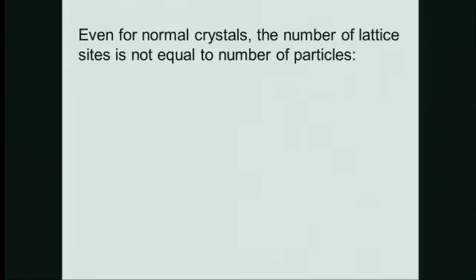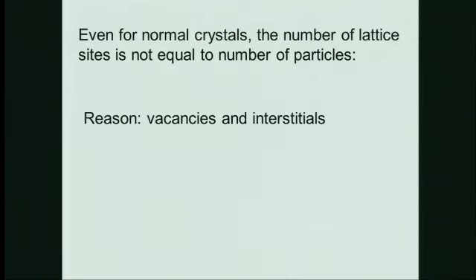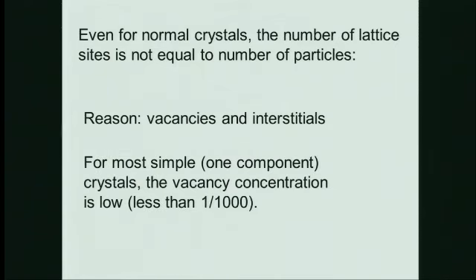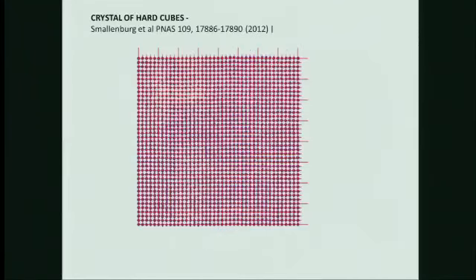So, okay, now even for normal crystals, the number of lattice sites is not equal to the number of particles, but that's because of vacancies and interstitials. That is trivial, and for most simple one-component crystals, the vacancy concentration is really low. Even at melting, it's typically of the order of 1 in 1,000 or less. Surprisingly, that is not always true. And that's the last thing I want to show.